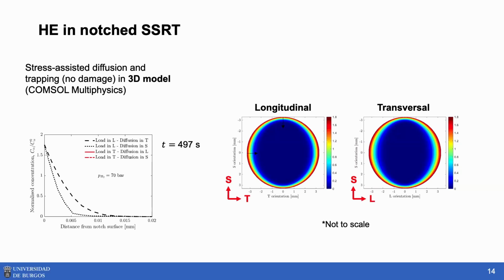This is in the longitudinal orientation of the specimen, and we can observe both diffusion into the T and S direction. Of course, since the tortuosity through the T direction is faster, we are going to observe higher penetration distances, and the same for the sample in the transverse direction for the hot roll plate.